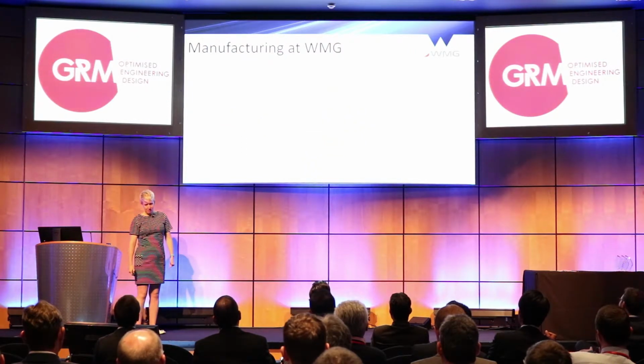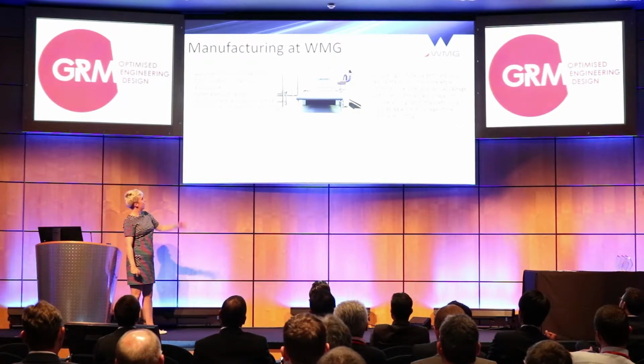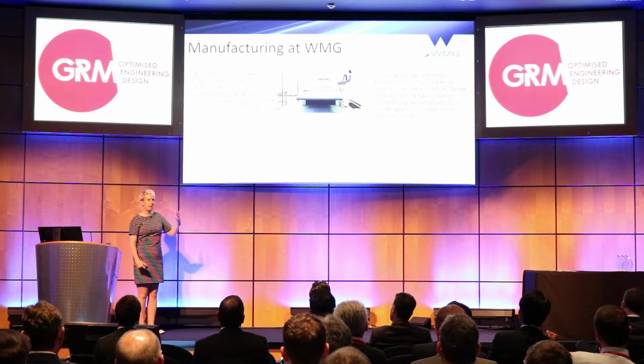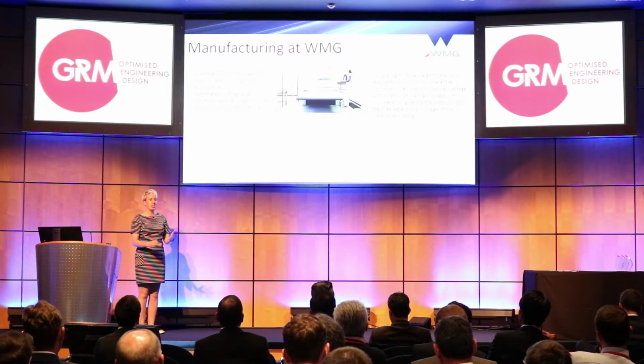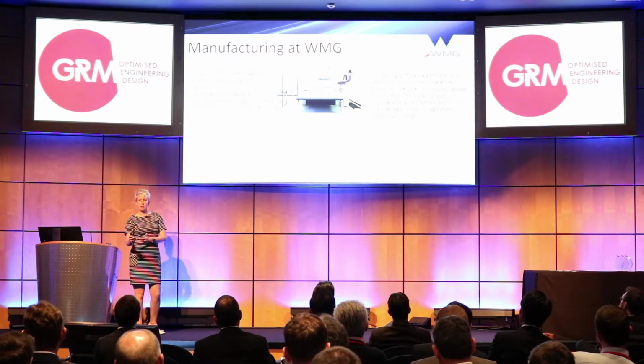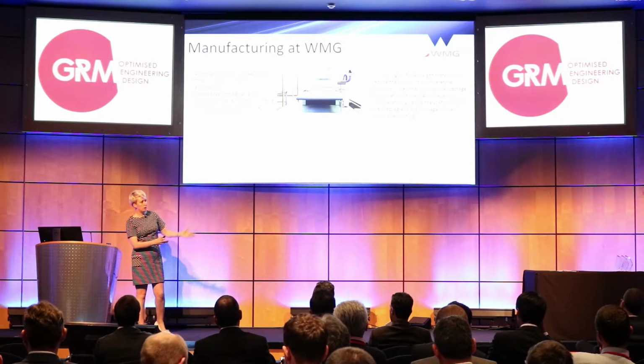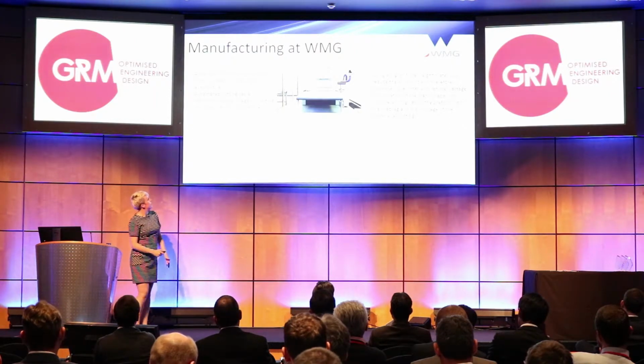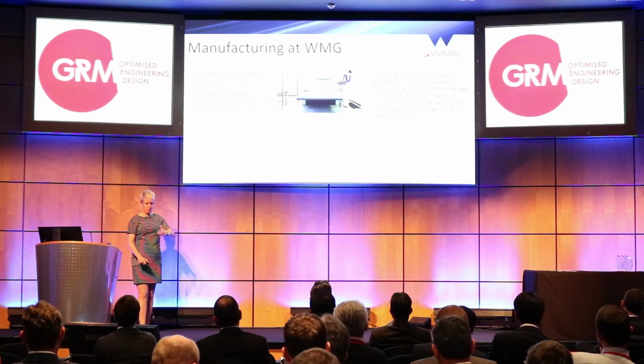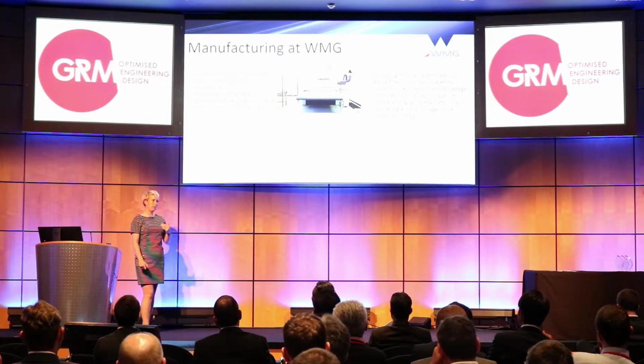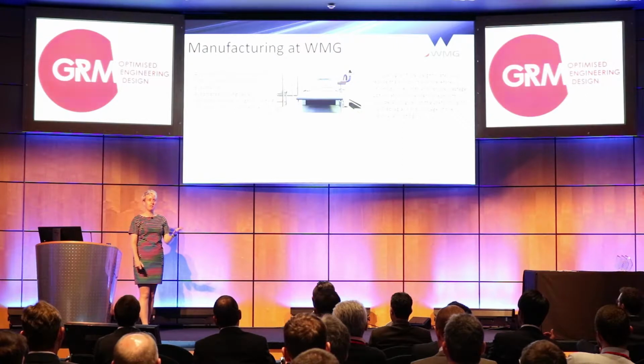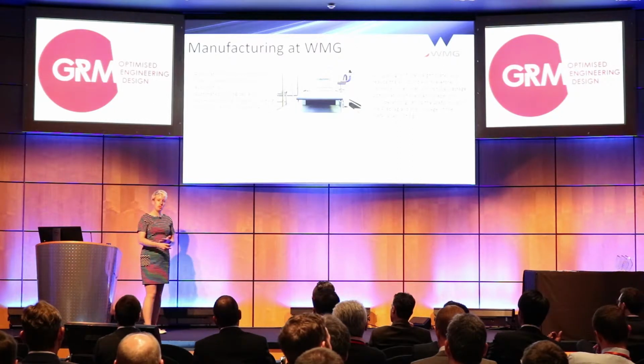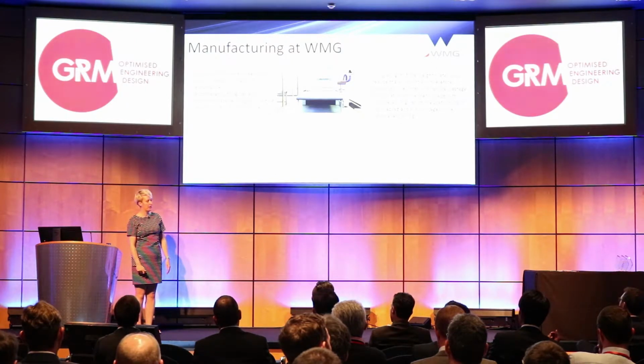So at WMG, we have an automated cutting machine. We felt it was very important in this project, when we were introducing this technology step change, that we didn't just do everything by hand going up to it. We wanted to show that you could use automation in all the preceding manufacturing steps as well. So we cut by automation, a ply cutter, simple. It was quite slow for us. We thought this was about 8 minutes per cycle. However, we were using off-the-shelf materials, so there were 19 plies within the part. In reality, what you'd do is use a higher weight material and cut fewer plies, so you had to lay up less. So we think that can be overcome.